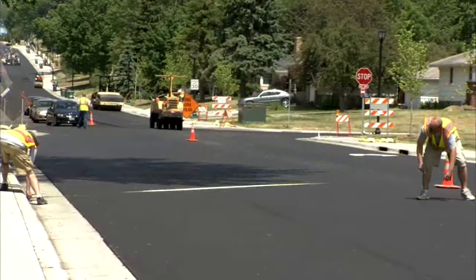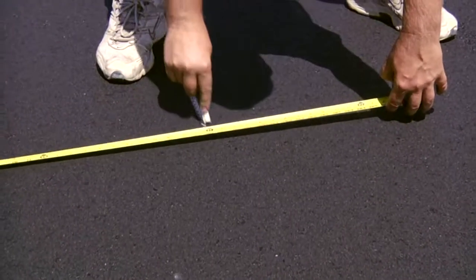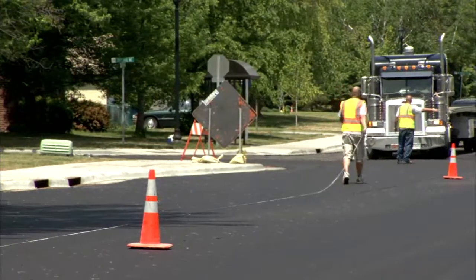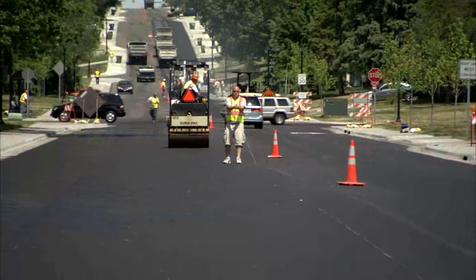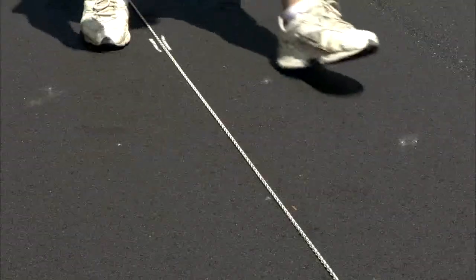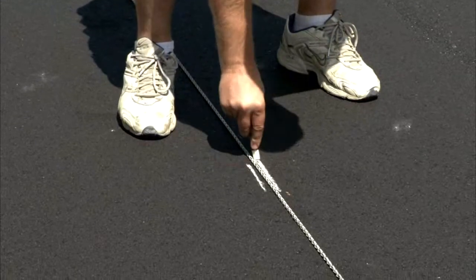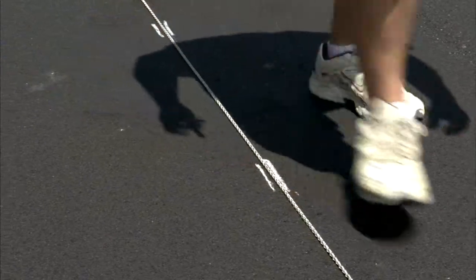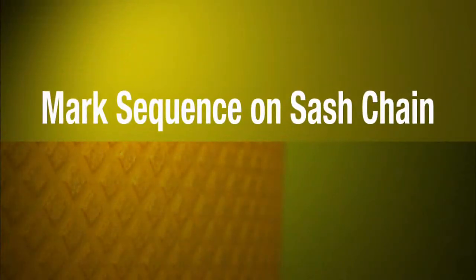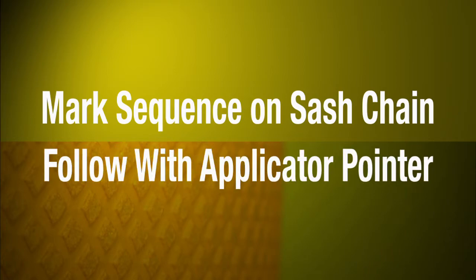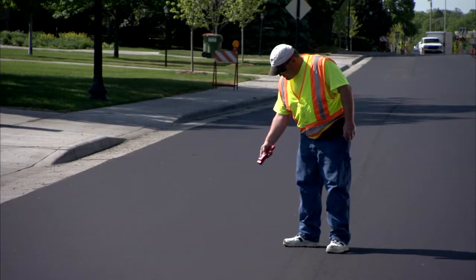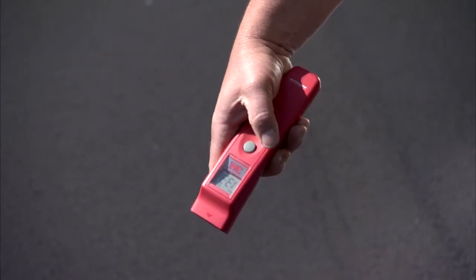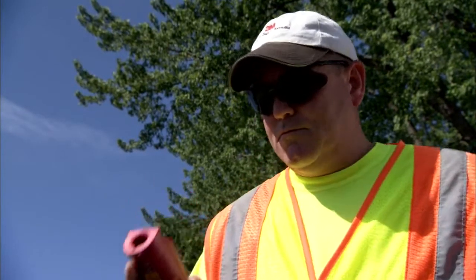As soon as the asphalt has been compacted, pre-mark the road. For long line applications, use 200 to 250 feet of sash chain or thin wire cable as a guide, or snap chalk lines on the asphalt. For skip lines, mark the skip sequence on a sash chain or with chalk or paint to be followed by the tape applicator pointer. Use a non-contact surface thermometer to frequently test the asphalt surface temperature until it is within